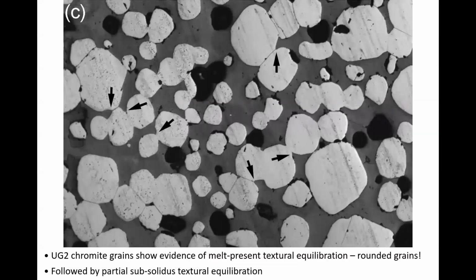And that's because what we've had is subsolidus textural equilibration. So this used to be beautifully rounded. It used to look like the experimental charge, with a low dihedral angle of about 30 degrees. The melt was replaced by plagioclase, and the plagioclase chromite dihedral angle is not 30 degrees. It's probably about 90. It might even be as big as 100. And if you zoom in at these arrowed junctions, you can see there's actually a break in slope as you get partial textural equilibration and a widening out of that three-grain junction. It's really very, very clear. There's a really obvious one right there.